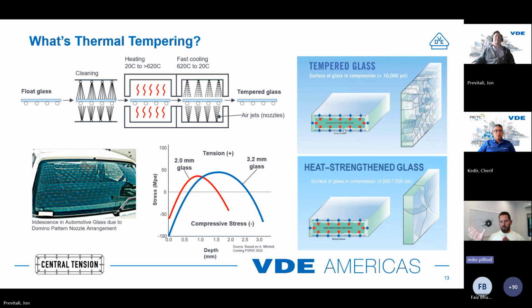When you go to 3.2 millimeters and you cool it down, you have more thermal mass inside of your glass. You freeze the surfaces, and it can pull them into compression. You do two things. One is you get a little bit more surface stress on it, as well as a bigger depth of layer because your glass is thicker.